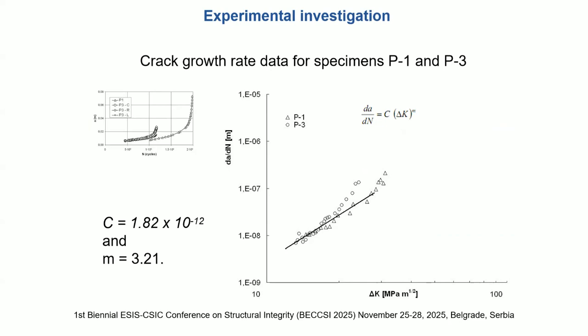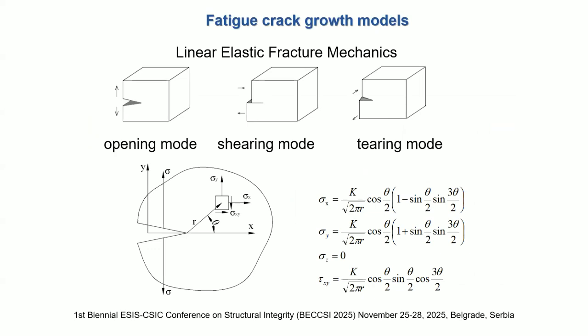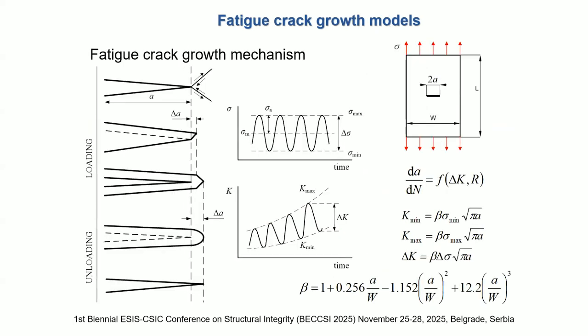And this is what we obtained or analyzed experimentally, and we want to simulate this. And for this, we will use Paris equation as shown there. And as mentioned before, we generate a crack growth rate diagram, and from this we obtain constants like C and M as shown here. And basically we have here mode 1 opening, only mode 1. And this is how we look at this program. The cyclic loading, we have crack extension for each cycle, some delta A, and then use Paris equation to simulate this.